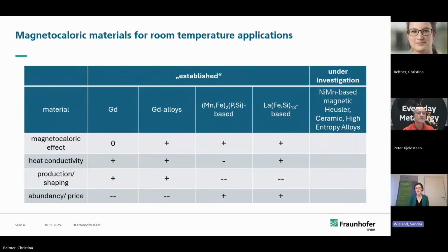And the reason why this is so important, maybe Christina can show the overview over the materials that are existing for magnetocaloric. We have a little picture just so that you can see something when I'm talking about all these material names. Maybe it makes it easier. So as I already mentioned, gadolinium was kind of the first material which was ever used. Gadolinium has a nice magnetocaloric effect at room temperature, but its effect is not very high. It has a broad temperature range where it's actually working, but the effect is not very high. It's a so-called second order magnetocaloric material.